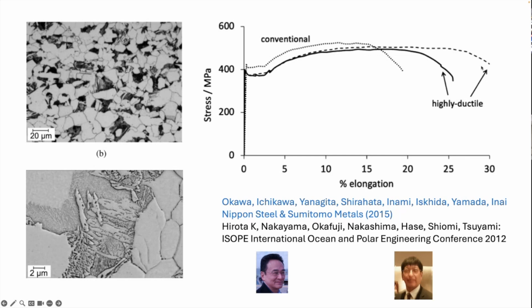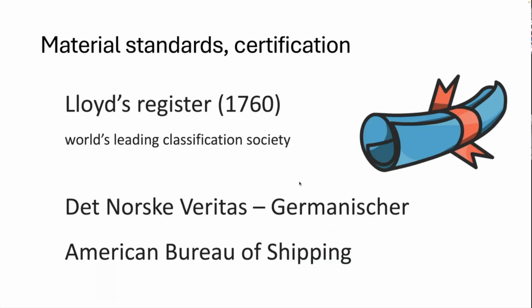But if you make these hard regions more homogeneous by introducing new structures as well, then you can get much greater ductility. And this is Kazutoshi Ichikawa, who was my PhD student, and Kazu Hase, who was a visiting scientist in Cambridge. They have designed a new ship steel, which has much greater ductility than conventional ship steel. Now, the test that I've illustrated here is very simple to do, but we really need to do much better than just a tensile test, because all these authorities which govern the construction of ships and the safety of ships must be satisfied, which means that you must be able to do tests on a large scale.